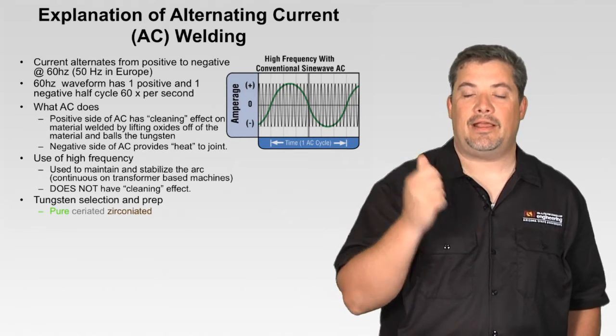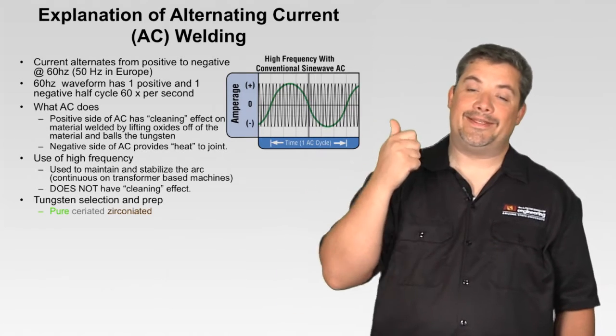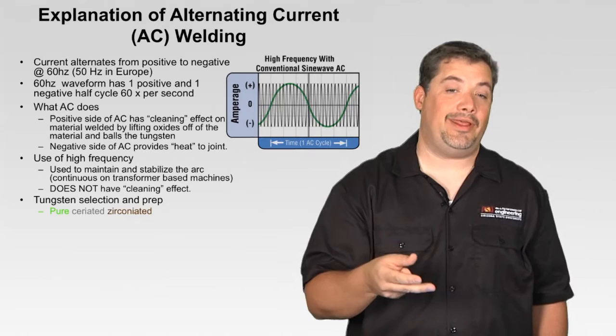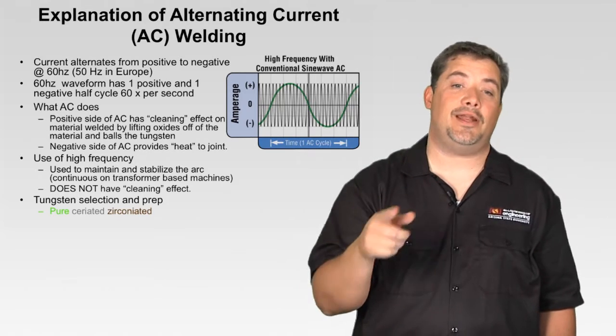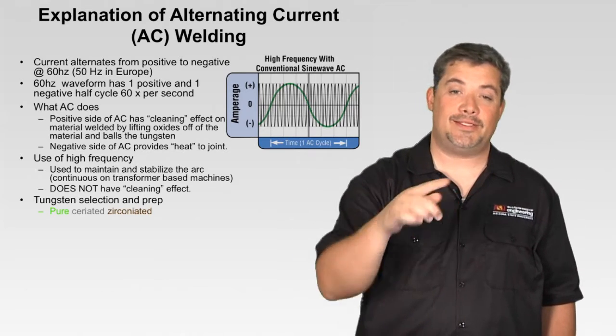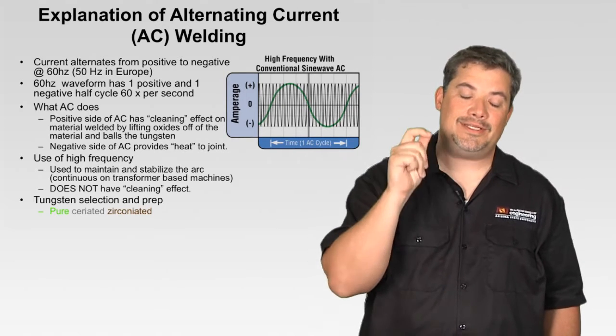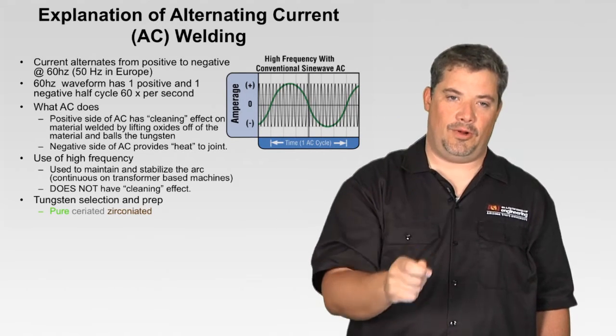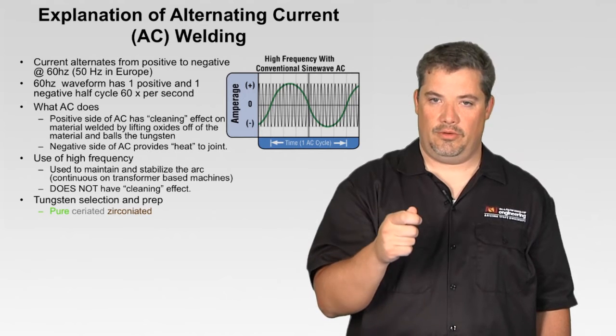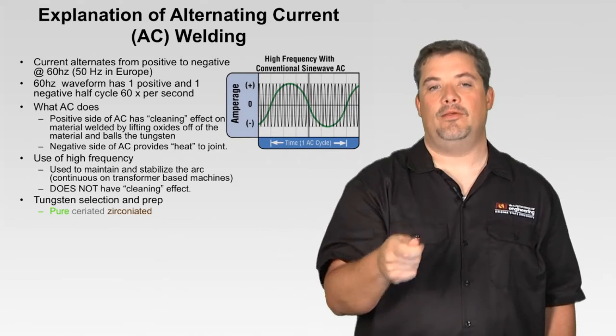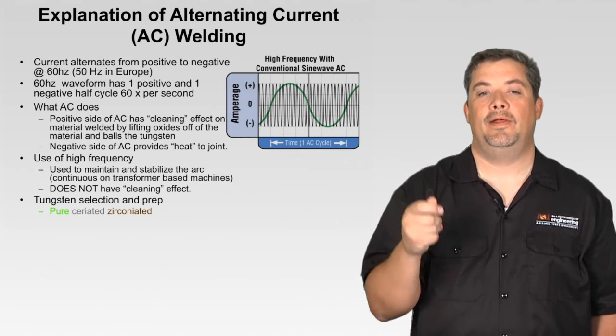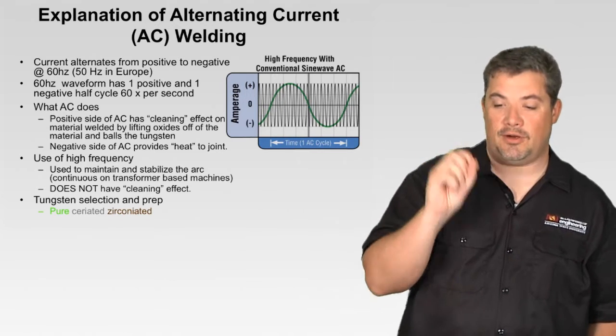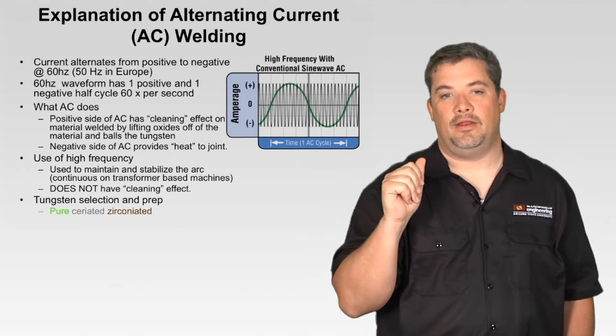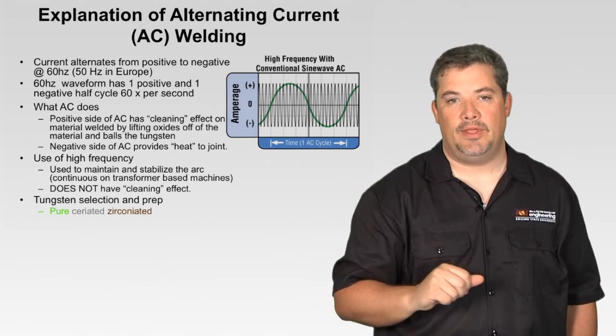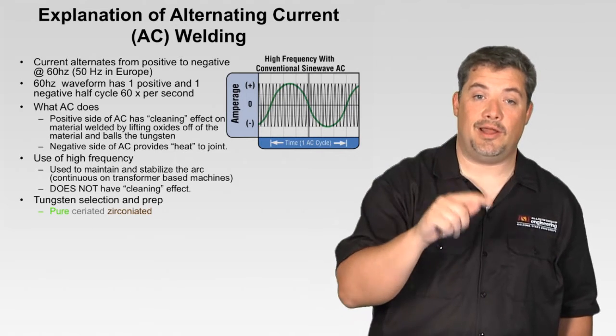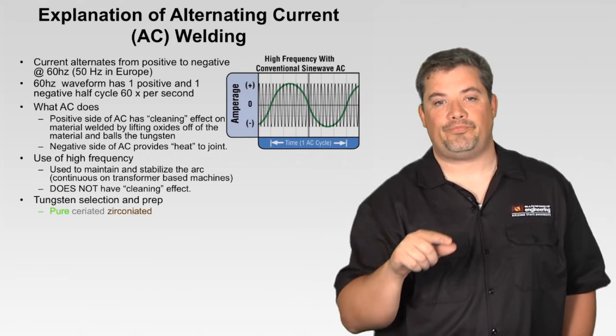So high frequency is used to maintain and stabilize that arc, and it's continuously used on transformer machines. And contrary to popular belief, it does not clean or etch or get rid of anything. It doesn't create that white etching along the side of the weld. It affects it, sure, but that's not what's creating it. High frequency only stabilizes and starts that welding arc. It has no other purpose in the AC welding arc. In DC, high frequency only starts the arc and it shuts off. In conventional AC, it's on all the time, and in the advanced AC, it's only on to start the arc, and we'll see why in a little bit.